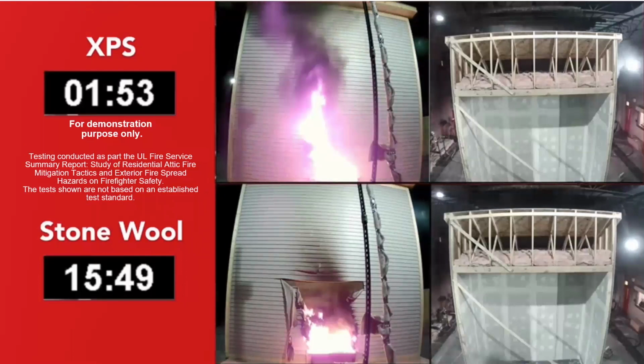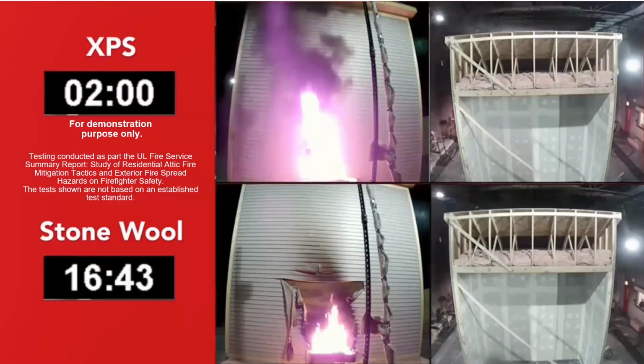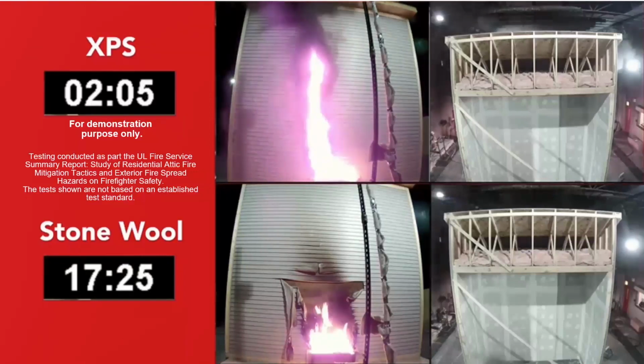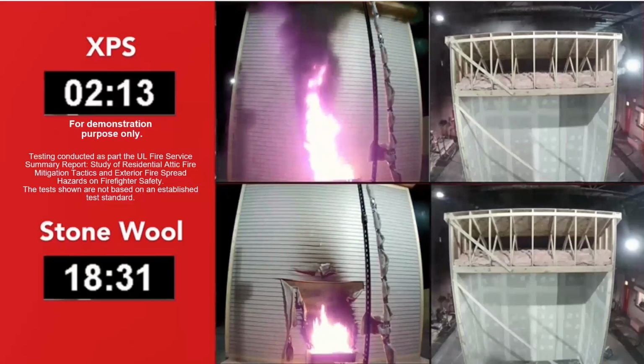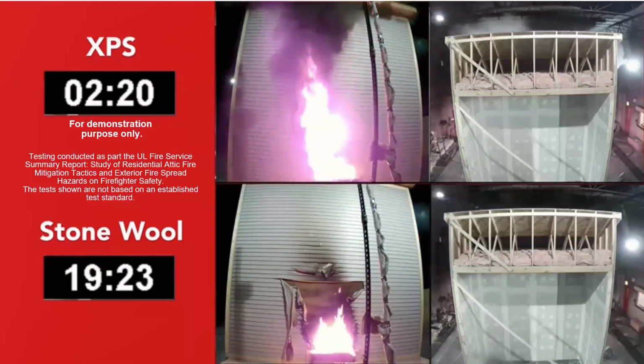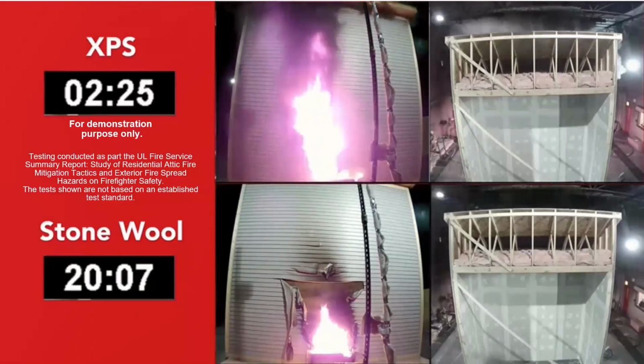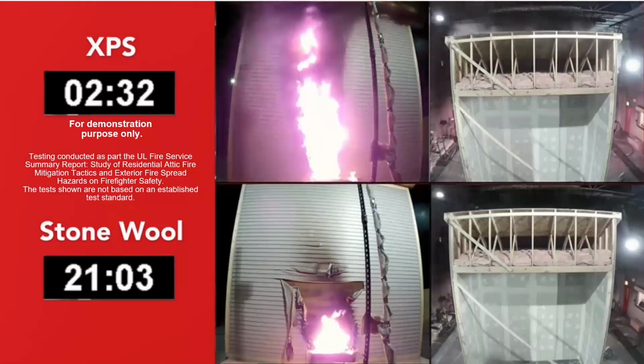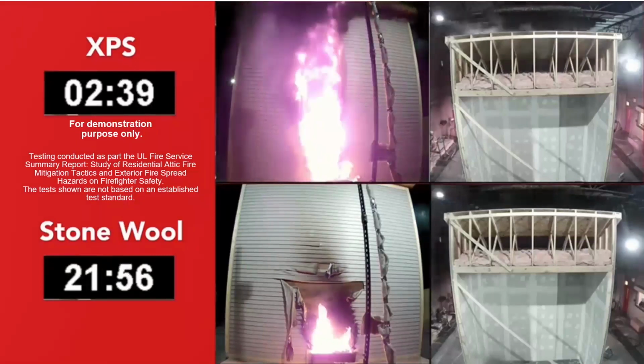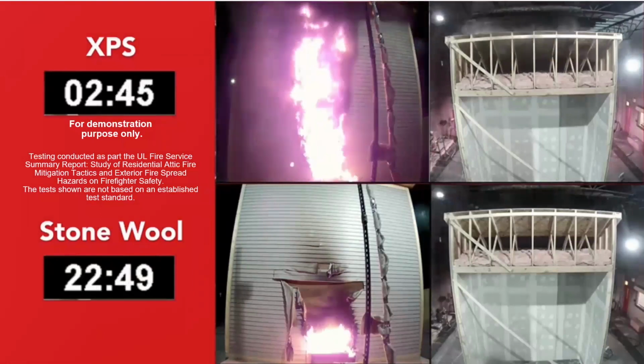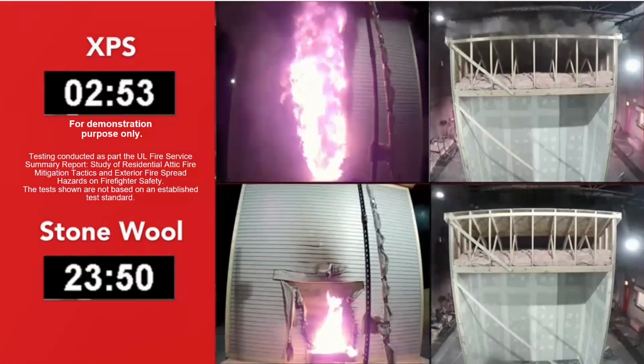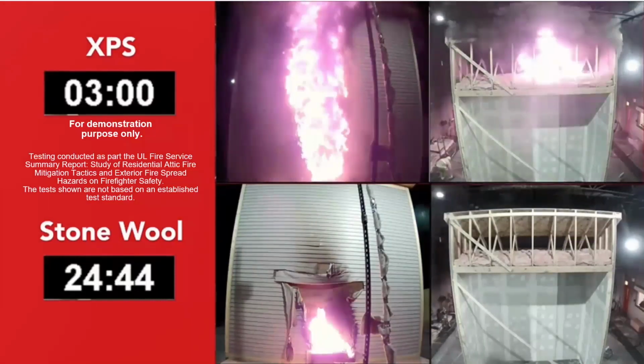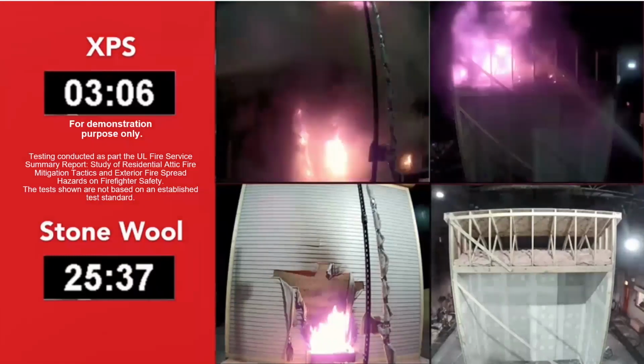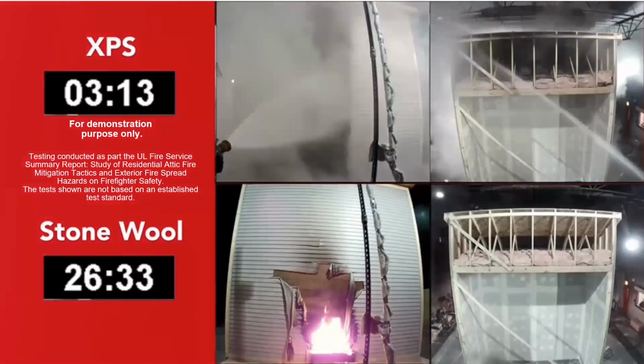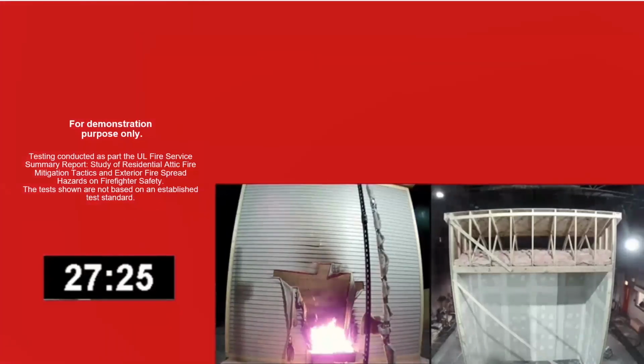So, what we're looking at here is, they started a fire at the base of each of these walls, and they're kind of measuring the time it takes for that fire to enter the attic space of this wood frame construction building. And so, we've had to push the stone wool clock fast, because after 30 minutes, they ended up having to shut this test down without the fire really moving past the vinyl siding. But you can see with the XPS wall above, I think in just under 3 minutes, it enters the attic space, and they have to diffuse it and kind of put the fire out. So there you'll see right at 3 minutes. So it's kind of an interesting visual on why, from a fire perspective, there has been this movement towards a non-combustible insulation, and I think we'll start to see some of these tests referenced moving forward in a lot of the codes.